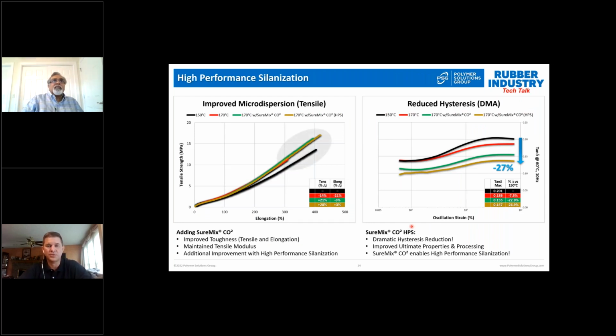Okay, so using the higher temperature silanization, right? I mentioned that you're going to drive the reaction and improve the dispersion of the silica. But in the case of the control compound, going from the black to the red on the left, if you look at the tensile, you see an increase in the modulus for all of the compounds at the higher temperature. And that's due to the liberation of the sulfur from the tetrasulfide due to the higher temperature.